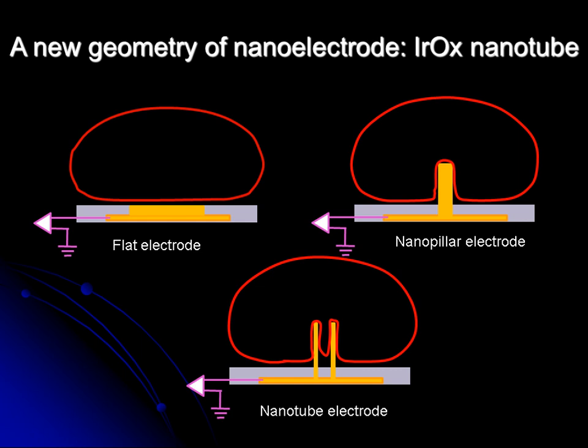We have done the TEM studies to see the gap junction between the cell membrane and the electrode is much narrower on the nanoelectrode compared with the flat electrode. So the interface is crucial for us to get a really good performance for electrophysiology recording. And then we think if we can further improve the interface, how the cell membrane interacts with the electrode, that will allow us to further improve the performance.